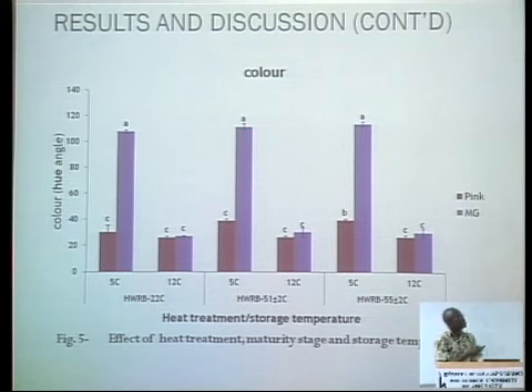And one thing we should know is that color also plays a very important role in ripening, because as fruits ripen, they change color. So the color is an indication of whether the fruit is ripening and whether it's deteriorating very fast. So if we're able to inhibit color change at a certain temperature, then it means that we can prolong the shelf life of the fruits. And the heat treatment was able to do that for us, especially in the mature green than in the pink. Okay, thank you.